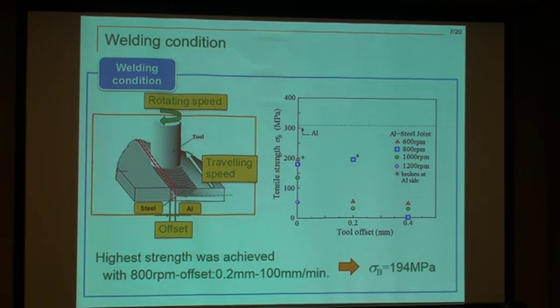Before we conducted the fatigue crack propagation test, to find out the appropriate condition, we did the tensile test with different welding conditions. We changed the rotating speed and the offset, which means the distance between the interface and the surface of the tool pin. And we set the traveling speed constant at 100 mm per minute. And this is a map of the tensile strengths depending on the welding conditions. As you see, the highest strength was achieved with 800 RPM and an offset of 0.2 mm.